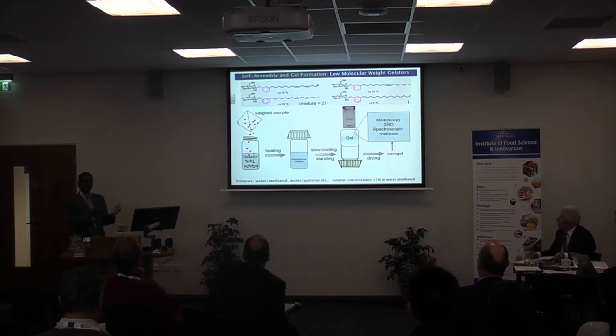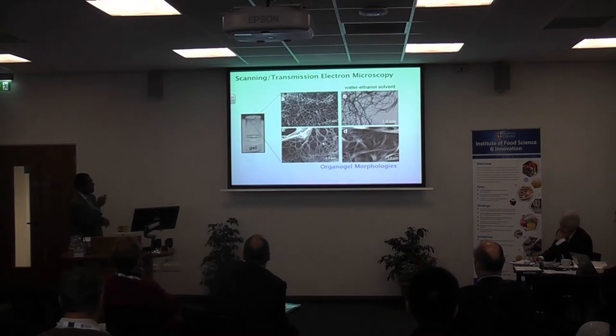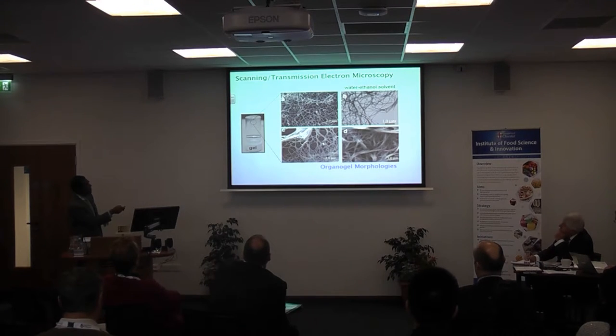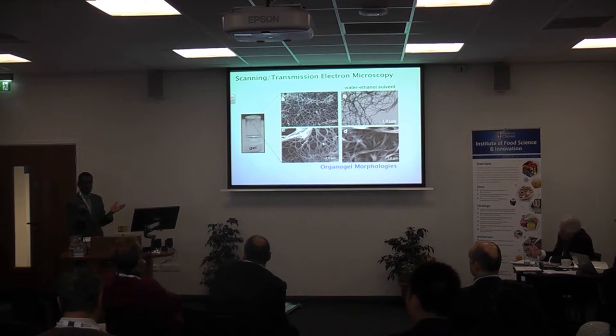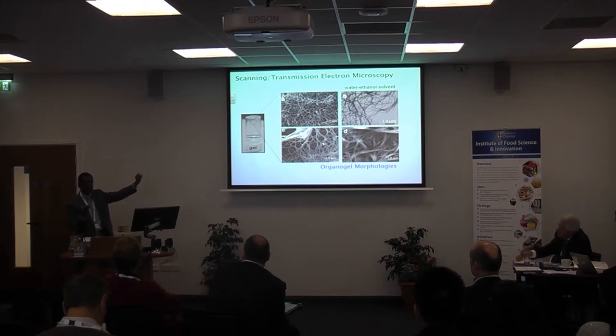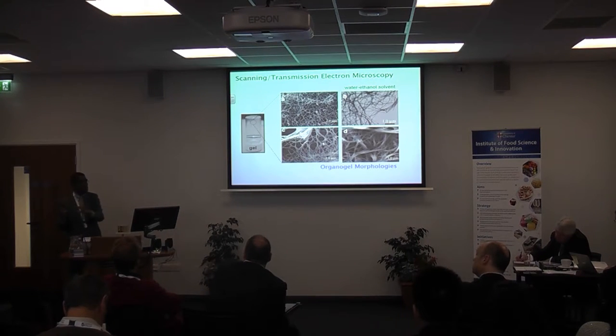Then we do the typical material characterization, to see what is inside. You can see all these fibers are at the nanoscale, at 20 to 30 nanometer diameter and very long. The aspect ratio is high. Whenever you have length to diameter aspect ratio high, we call them nanomaterial. And this is not a nanoparticle, not a metallic nanoparticle. These structures are created from simple lipid molecules through assembly, utilizing the weak forces of nature. We are creating a three-dimensional network.